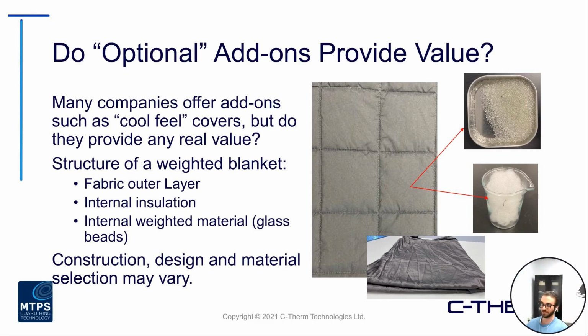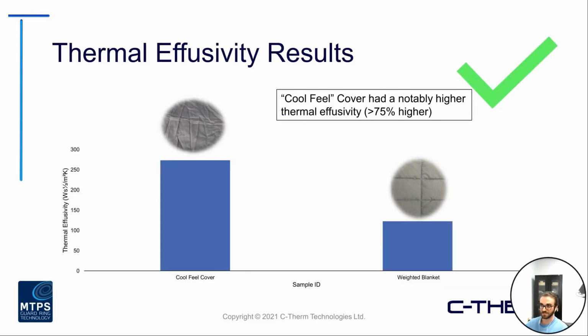So does the cool blanket cover provide any value for this type of product? Well, through some of the testing that we've done, it showed there was quite a significant difference in thermal effusivity from that outer surface cool blanket compared to the weighted blanket itself. About greater than 75% more cool feeling with respect to that add-on. Now, of course, you have to weigh the cost differences between some of these add-ons from different companies. But again, this is just one way that you can make claims and back up those claims to really prove why this specific product or add-on is going to add value to your end user. And in this case, again, showing quite a significant influence here.